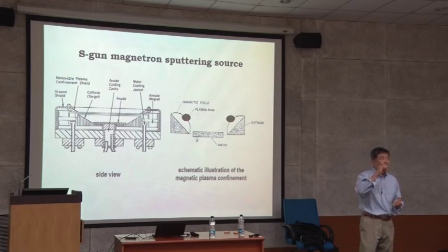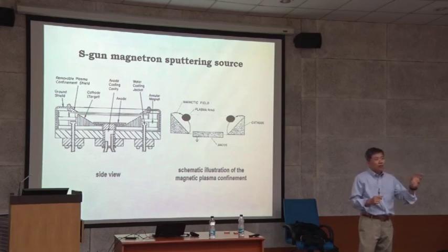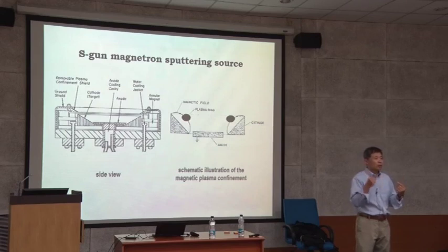So then you have two ways you can do it. One, make the target thin, or you buy a sputter gun with a stronger magnetic field. So you can ask the vendor, we are going to sputter magnetic material, can you provide a stronger magnet sputter gun? So you have two ways to do it. A simple way, without buying a new sputter gun, is to order the target very thin. A 1/16 inch target, rather than 1/8 inch thick, the standard thickness.